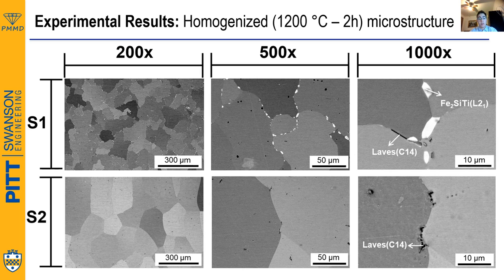EDS results of the L21 microstructure told us that this phase has a finite amount of niobium solubility. Niobium in steels is well known to segregate to grain boundaries during heat treatment. This then allows us to speculate that the diffused niobium at the grain boundaries might be acting as a heterogeneous nucleation site for the L21. And CALPHAD, since it assumes L21 to be a line stoichiometric compound with no solubility, won't be able to predict this type of behavior.